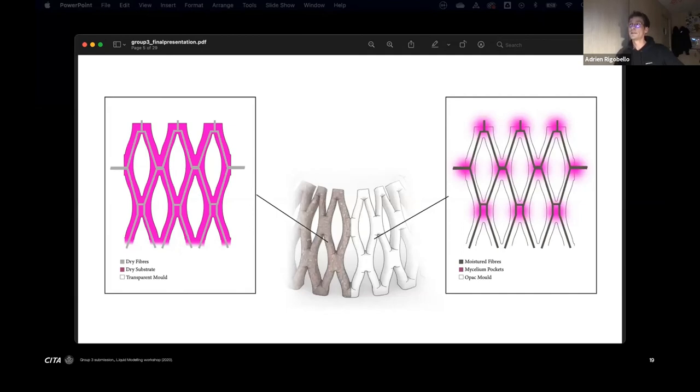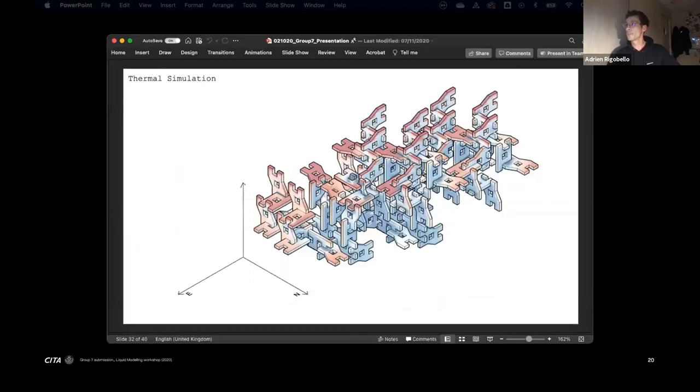The radiation analysis is thermal and is based on the boundary mesh of the work. Custom code was developed to interpret radiation data into a stochastic volumetric warmth map which can be calibrated to specific thermal conductivity of a mycelium-based composite. With this particular architectural technique, we can isolate nodes and iteratively simulate the moisture dynamics in the structure for predicting fungal colonization. The work is still in development, especially because it does not incorporate rainwater nor variations in relative humidity yet and requires a calibration marker at the one-to-one scale in outdoor conditions, which can be quite time-expensive. That being said, we have been using this simulation model to teach architecture students about mycelium-based composites craft, and through a very iterative process between experiments and simulation, they went on to calibrate the model with regards to moisture dynamics observed in control environments and fungal colonization speed and patterns.